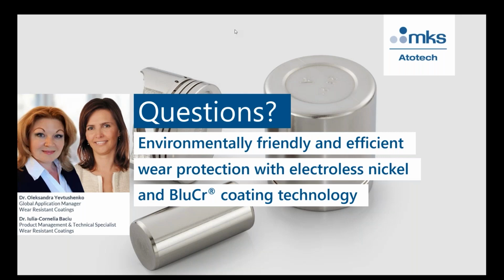Let me have a look. Next question. Why does a high P coating achieve the highest corrosion protection in the salt spray test? Yes, I will pick this question. This is because the high P coatings have the lowest deposition rate, so the coating process is the slowest, and the coating is building not very fast, and then we have the lowest porosity. So we have the highest corrosion protection with the high P coatings. And with these coatings, we have the lowest amount of defects. So it's the best coating for corrosion protection. Thank you very much.